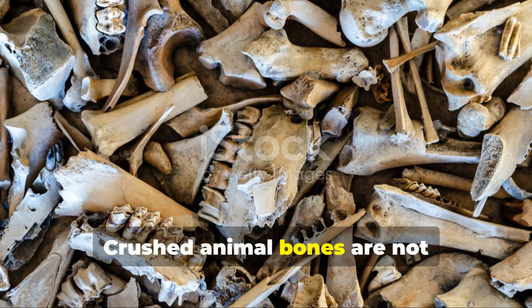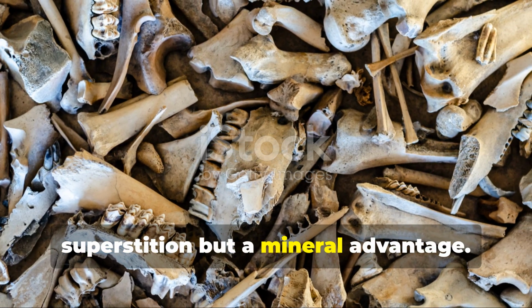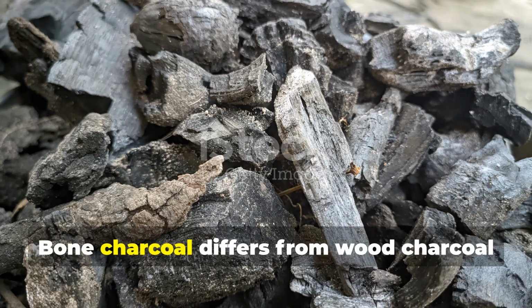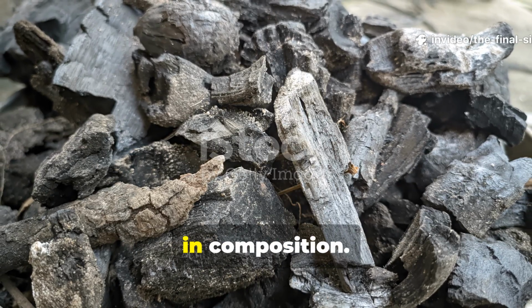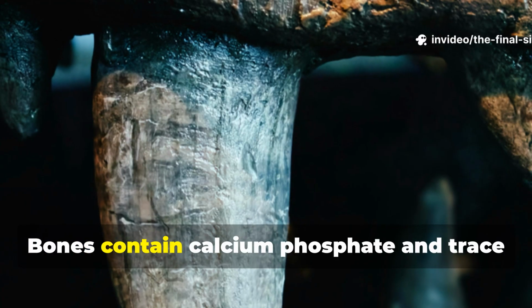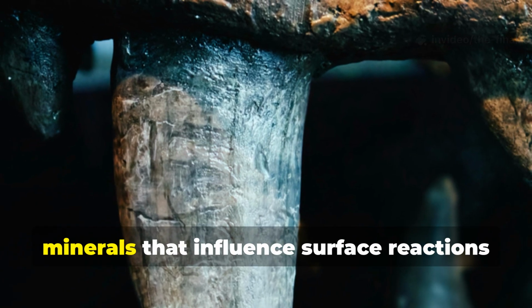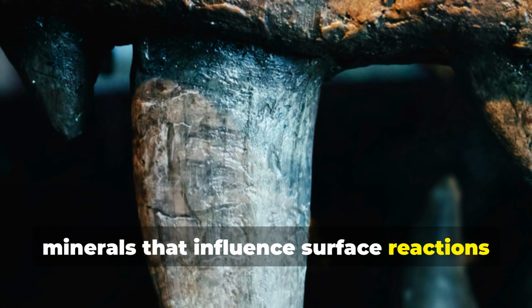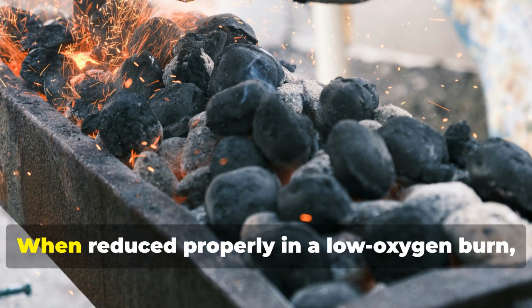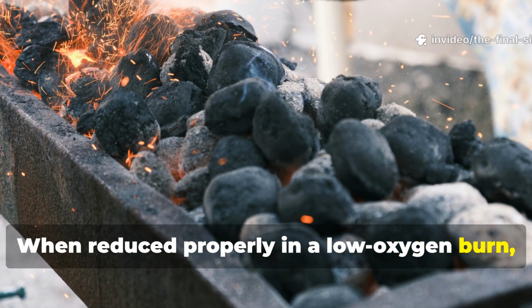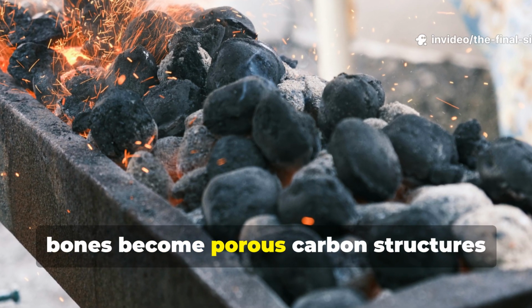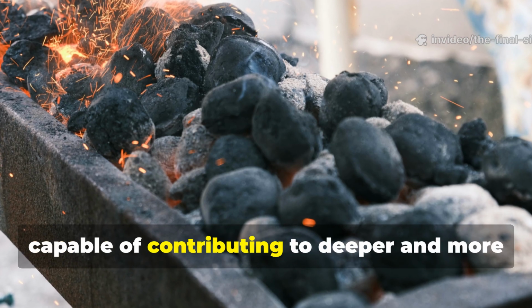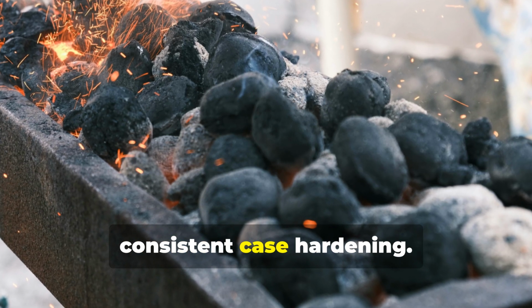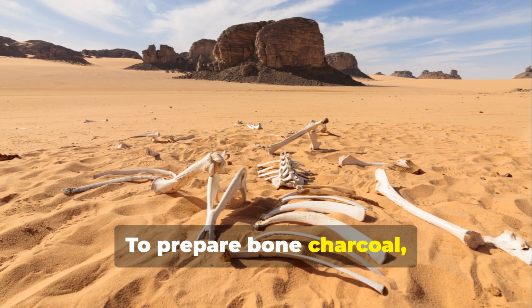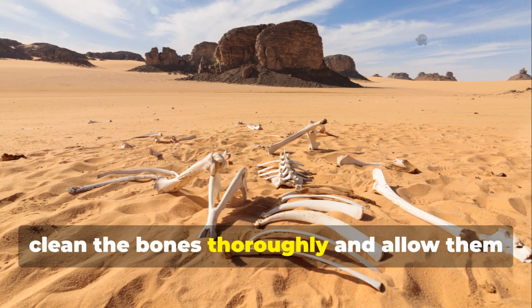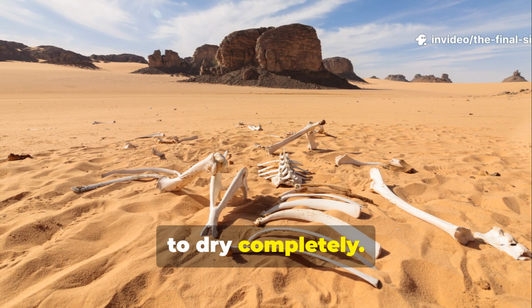Crushed animal bones are not superstition, but a mineral advantage. Bone charcoal differs from wood charcoal in composition. Bones contain calcium phosphate and trace minerals that influence surface reactions during carburization. When reduced properly in a low-oxygen burn, bones become porous carbon structures capable of contributing to deeper and more consistent case hardening. To prepare bone charcoal, clean the bones thoroughly and allow them to dry completely.